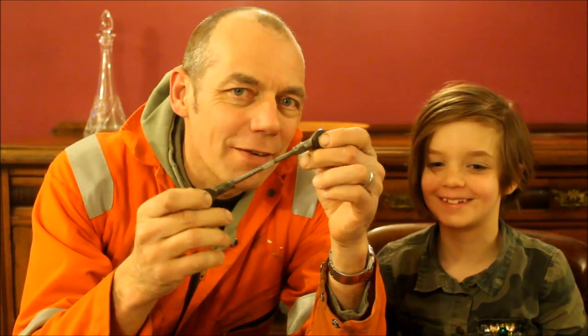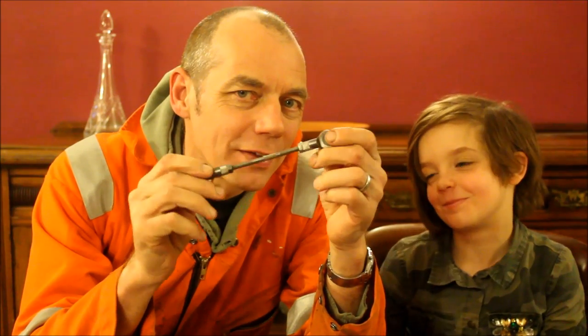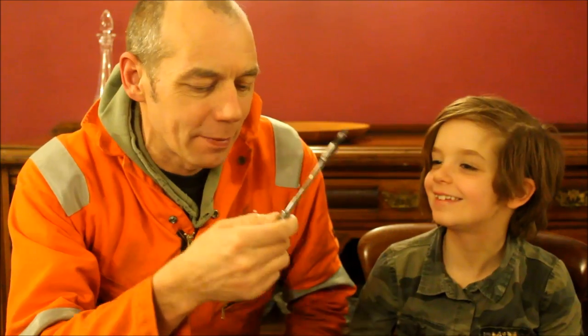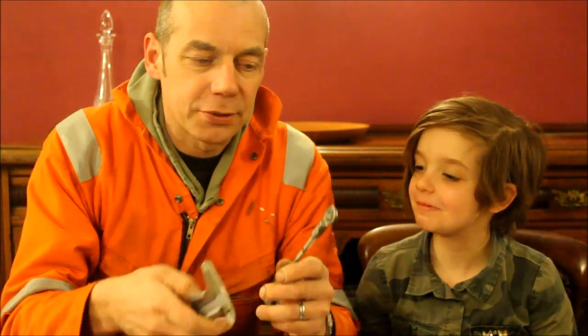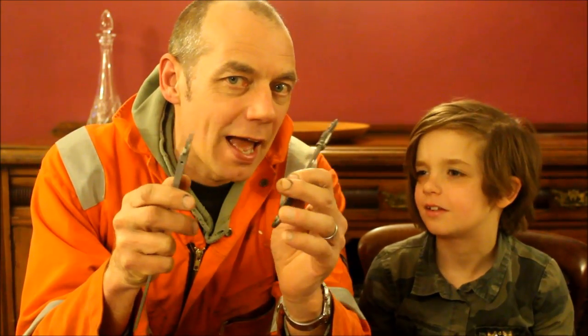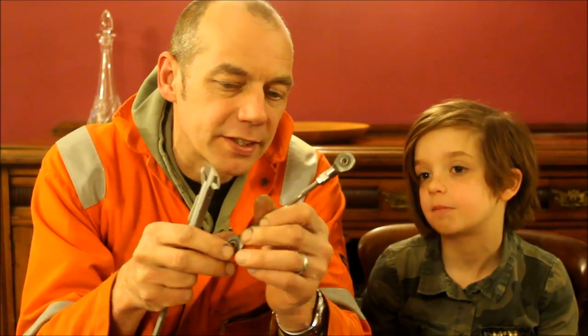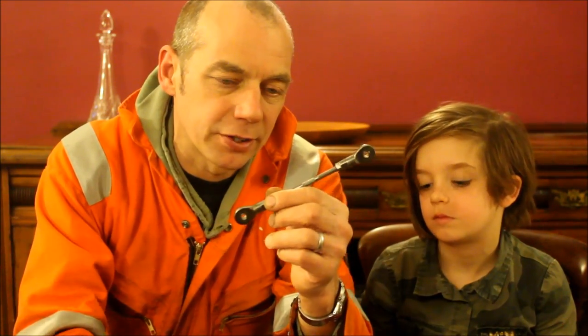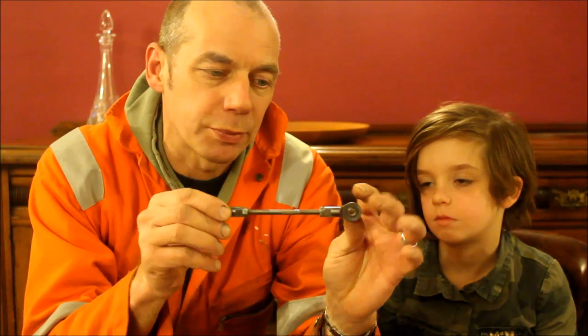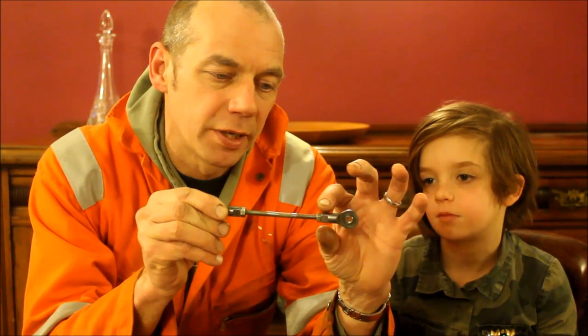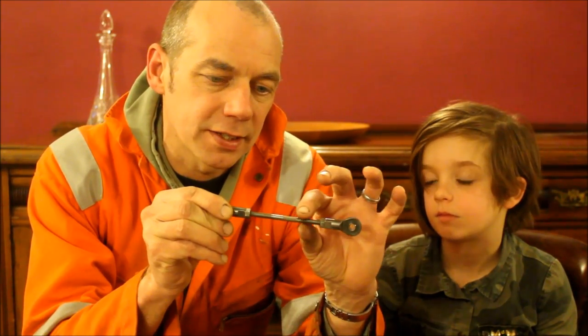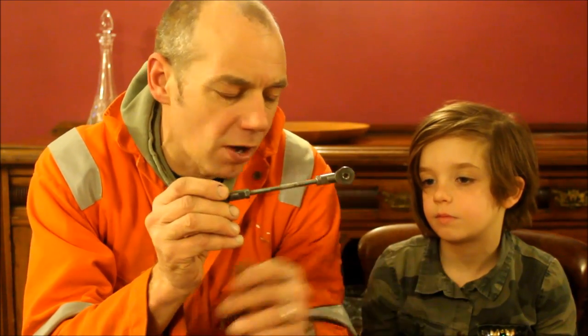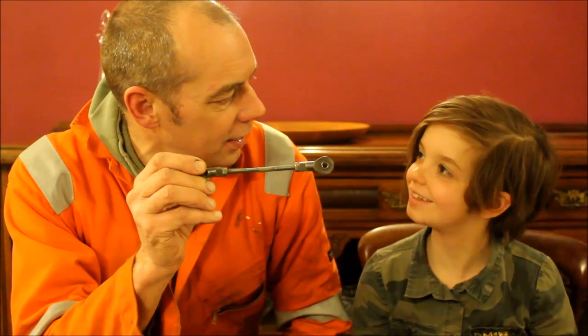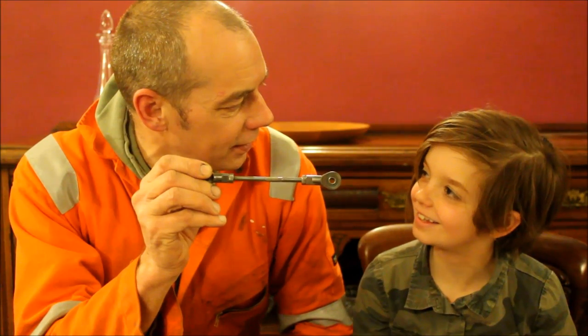So when you've got the surface rust off, the next thing we need to do is work out the surface area. There's a bit of mass involved, so I've got the helper to help me out here. So now, you don't need to do this with a micrometer, but you do need to work out the areas reasonably accurately. So just approximate them to common geometrical shapes. So for instance, for this, we can approximate that to a cylinder, which is 0.8 centimetres in diameter and 17 centimetres long. So Edie, what's the surface area of a cylinder?